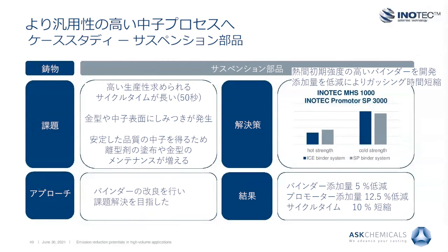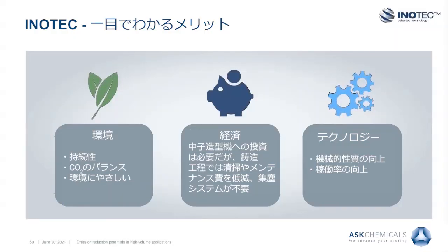The solution here is to customize the binder system to the process by providing a binder system with an adjusted strength profile. Inorganic binder systems for suspension part cores need an adjusted strength profile in comparison to cores for cylinder head castings or crankcases. Higher immediate strengths are necessary, lower final strengths are acceptable. As a result, the components of the binder system could be reduced, enabling a cycle time reduction of 10%.